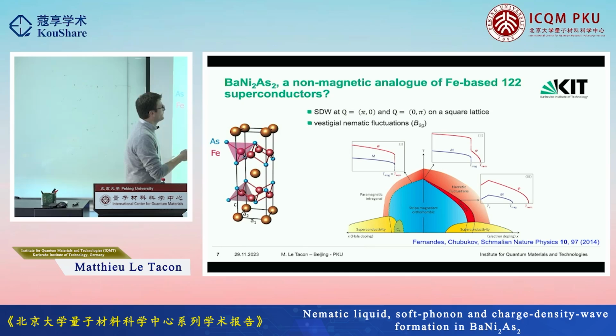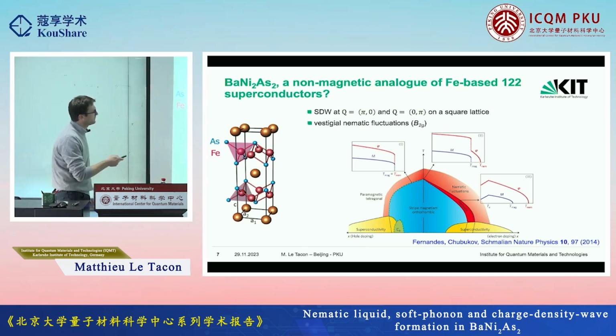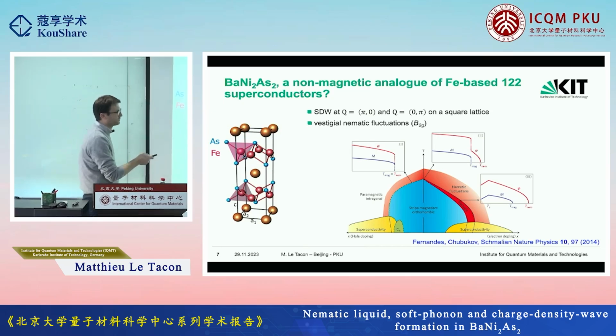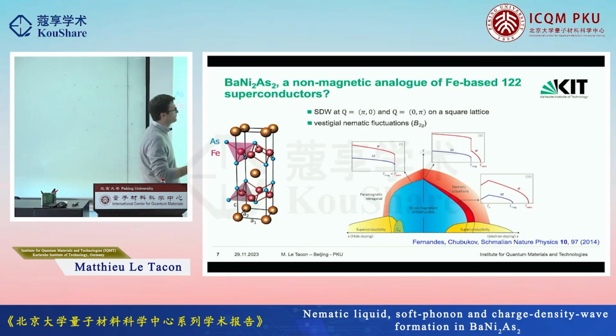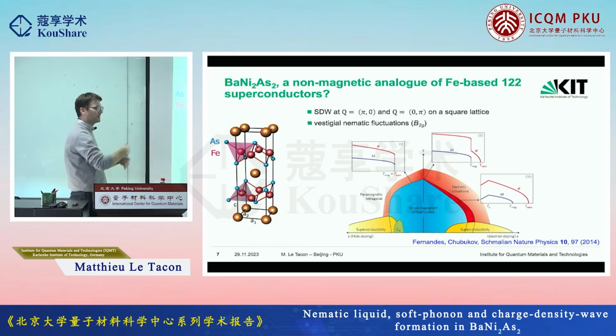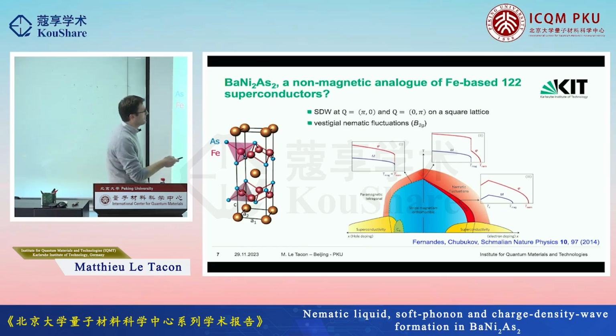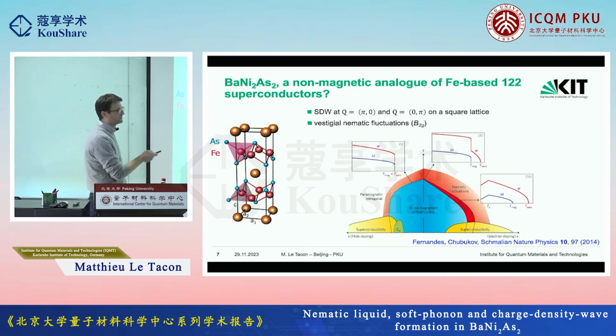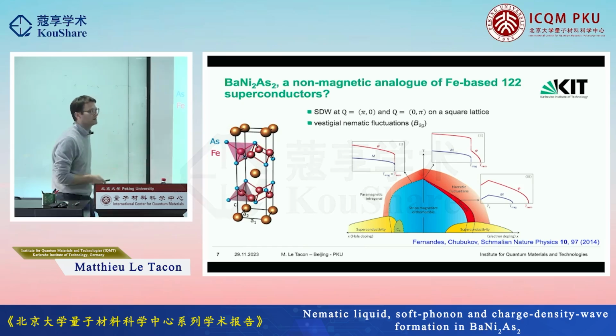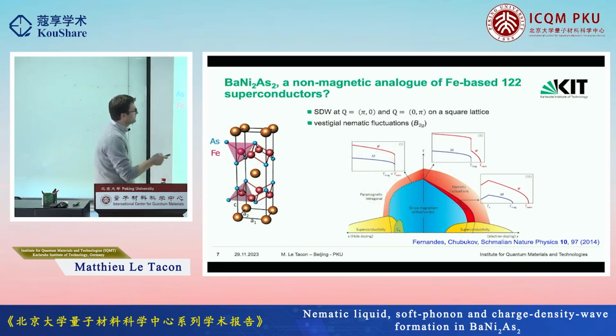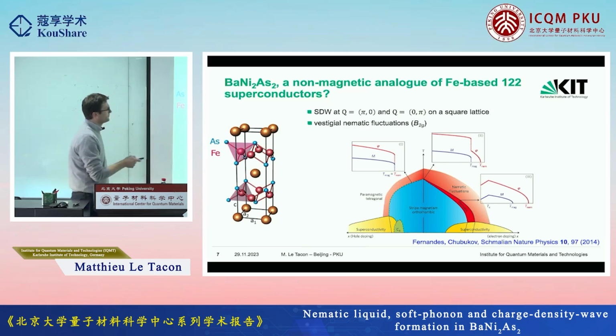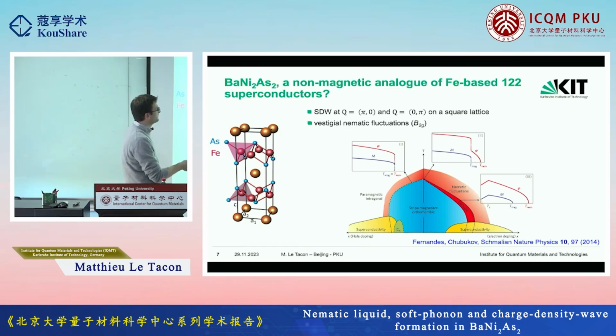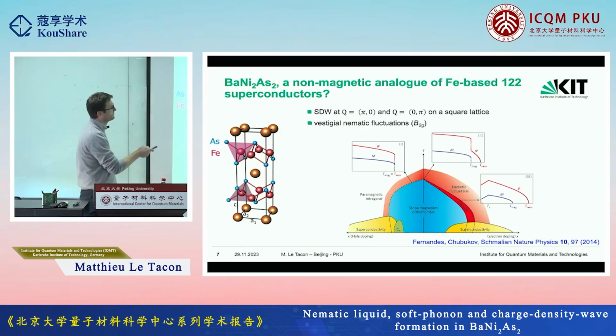So these are doubly degenerate orders, and nature doesn't really like degeneracy. And so you can create a new order parameter, which would read as basically the square of the order parameter along x minus the square of the order parameter along y, which tends to spontaneously take a finite value and break this rotational symmetry, so that de facto the system is going to choose either one or the other. It's going to favor one of these phases against the other. So this yields nematic fluctuation. As long as the system is in the tetragonal state, it is not chosen yet whether it wants to go to this one or to this one.